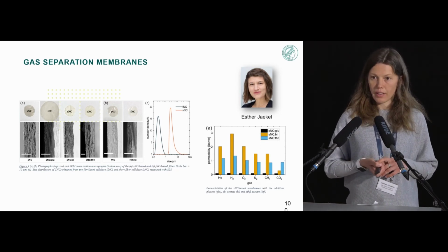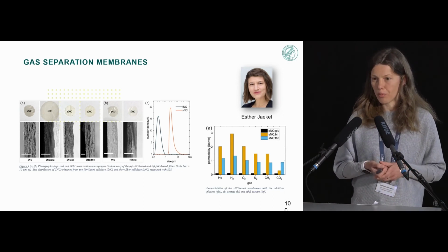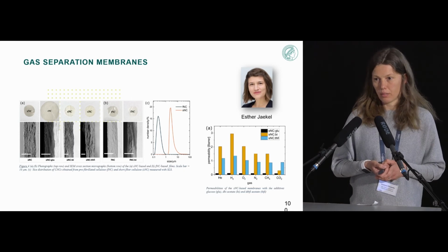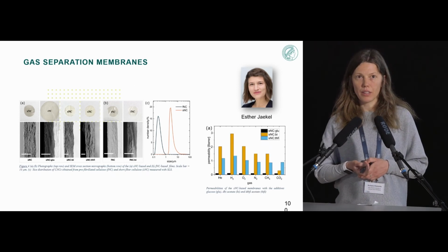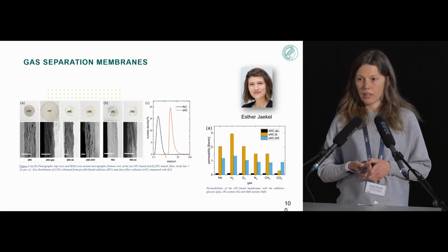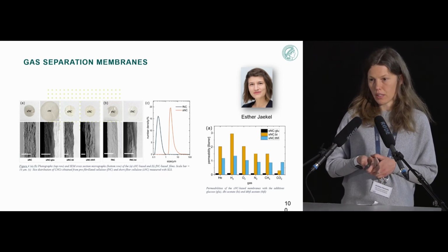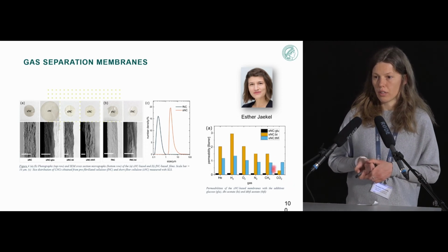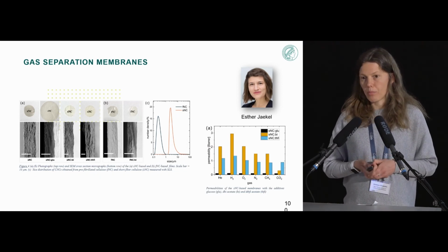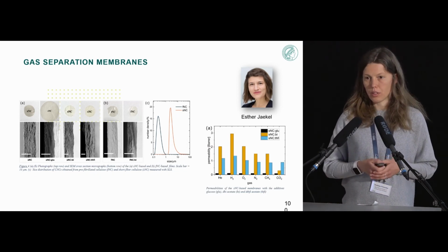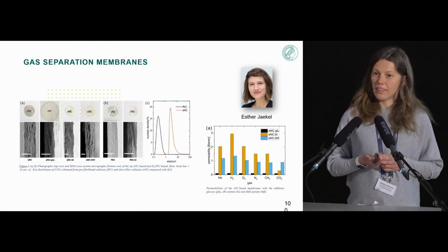But the interesting thing, which we found out by measuring these membranes, and we are still a little bit puzzled about it. This is some kind of weird interaction between the ionic liquids and cellulose, which gives absolutely counterintuitive gas separation. So CO2 basically goes slower than nitrogen, which is not expected, and probably somehow related to the interaction with ionic liquids, which is to be researched.